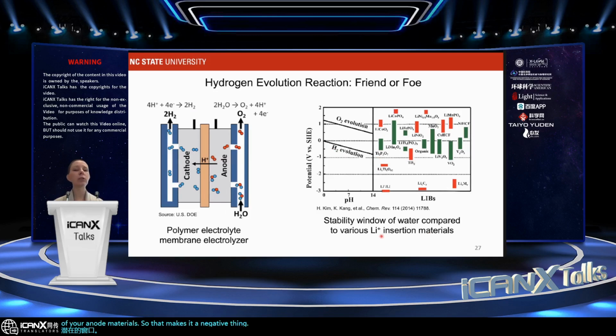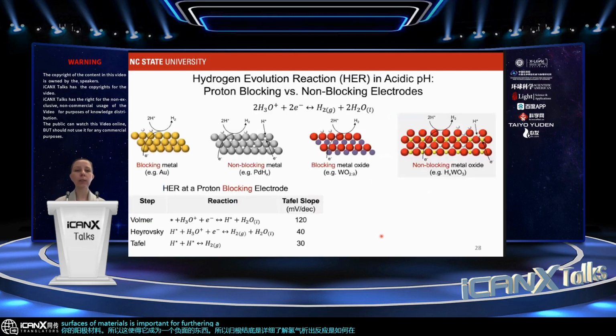So what it comes down to is that understanding in detail how the hydrogen evolution reaction proceeds on the surfaces of materials is important for furthering aqueous electrochemical storage devices. And so, as I mentioned, our interest in this was coming from the perspective that some materials, like the tungsten oxides, are going to allow protons to insert into the bulk, meaning that in the more classic electrochemical language, they are non-blocking electrodes for protons. And we can make some analogies to the field of metal electrodes, which has received much more attention on the fundamental side. So you can have metals like gold that are blocking towards protons, and the reactions are only happening on the surface.